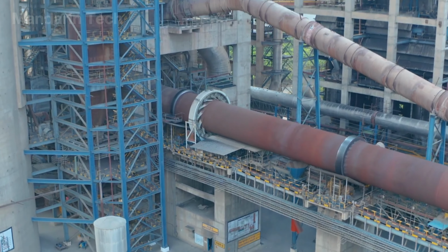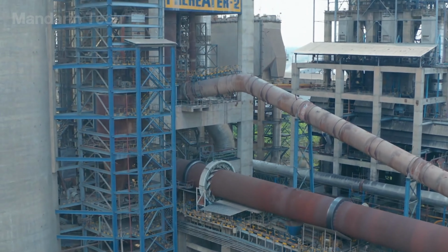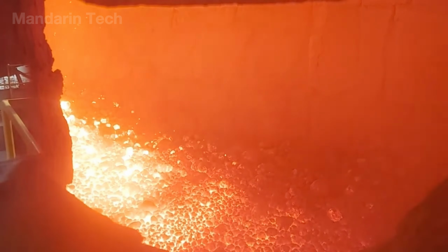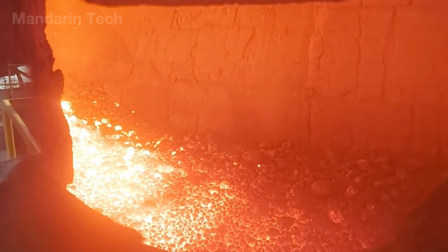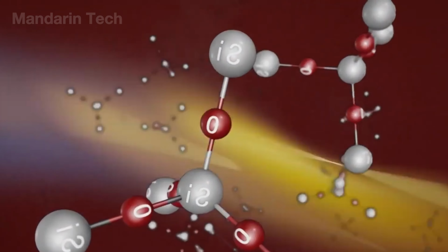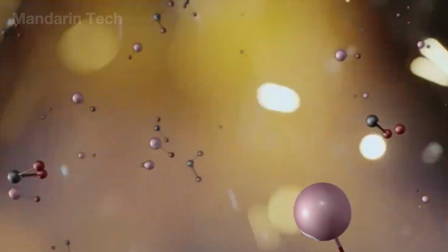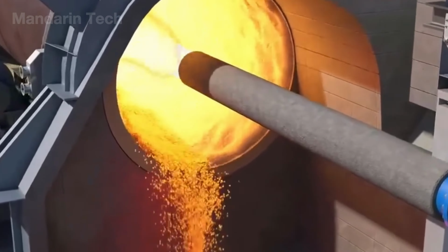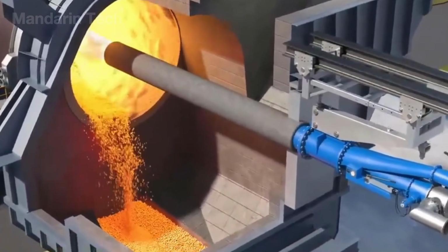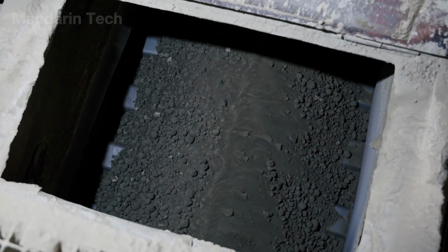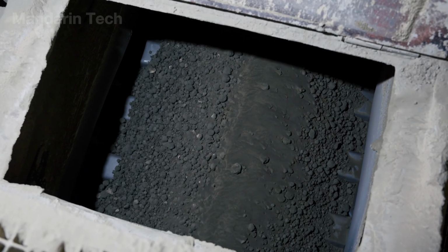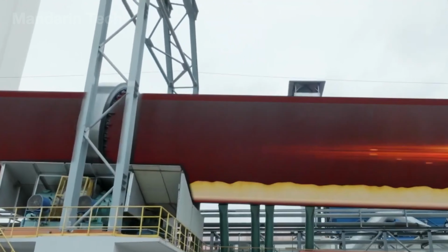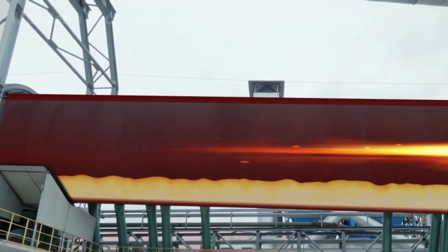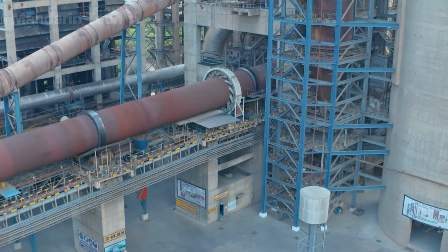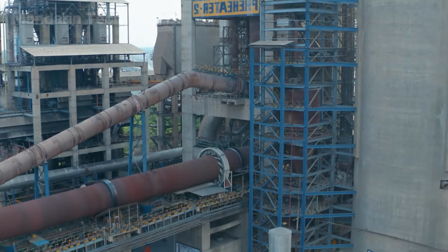At this temperature, CaCO3 rapidly decomposes, releasing CO2 and forming highly reactive CaO. The CaO then combines with silicates and aluminates in the mix to produce the key clinker phases: alite for early strength, belite for long-term strength, and aluminate for setting behavior. This is the most critical stage of the entire process, where even small fluctuations in temperature or retention time can cause underburned or overburned clinker.